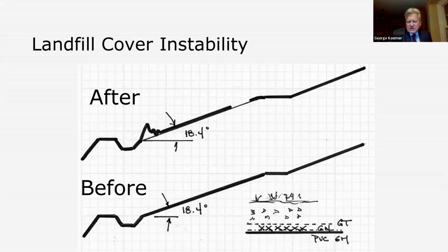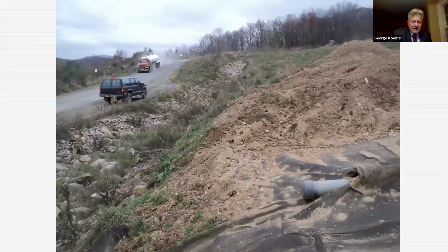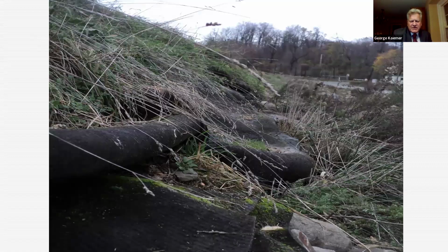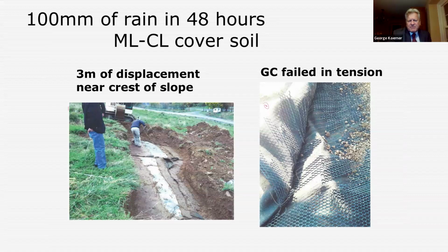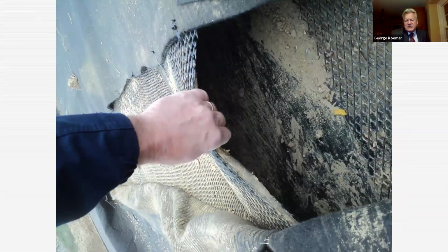So the cross section looked like a PVC geomembrane, a geocomposite made up of 2 geotextiles on the outside of a geonet, and then about a half a meter of soil over top of that. Here you see the gathering of the material at the toe, right in the drainage swale. Here you see it a little bit better. Where did all that material come from? It came from upslope. There was actually a breach. You saw a crack open, and then a ripping of the material up top. The failure was between the geotextile and the geomembrane.